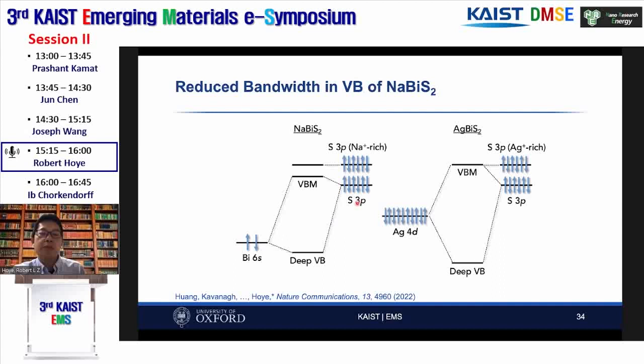And in the sodium-based compound, sodium acts as a spectator ion and doesn't take part in the band edges, the orbitals at the band edges. So we mainly have hybridization between the sulfur 3p states and the bismuth 6s states. Because these two states are relatively far away from each other in energy, we have a small splitting between the bonding and antibonding states in the valence band. And hence, we have a high concentration of states in the valence band.